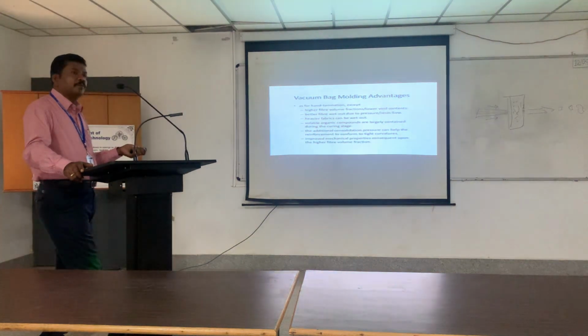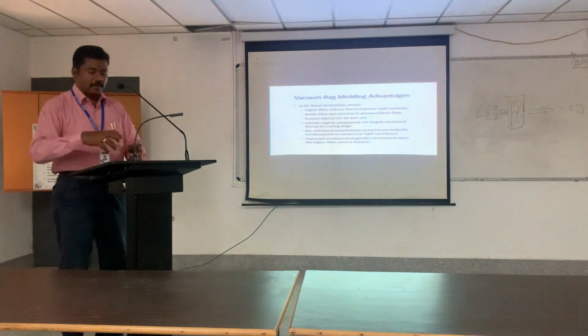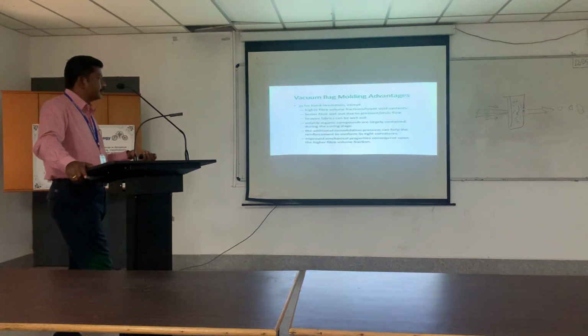Volatile organic compounds are largely contained during the curing. So if there are volatiles, they will be removed. Additional consolidation pressure can help the reinforcement to conform to tight curvatures. If any curved part is there, during vacuum pressure that will be exactly formed. Improved mechanical properties consequent upon the higher fiber volume fraction. That is the main advantage.